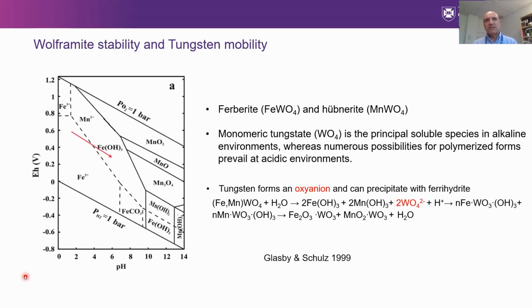As I said, it's really interesting to see that tungsten at that kind of pH formed this monomeric tungstate form, and this tungstate ion is absorbed to ferrihydrite. It starts absorbed to ferrihydrite, which is less stable, and gradually to more stable phases. You can see that it forms an oxyanion, just like arsenic, and is absorbed there. Then as the ferrihydrite starts to lose its water, it becomes more stable and associated with that fraction of iron oxide or manganese. So that's the stability around here for the tungstate ion.